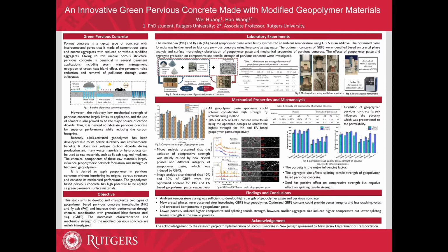After optimizing the formula, we use this formula to mix with aggregate to prepare the geopolymer pervious concrete. Here, the aggregate is limestone, and it has 4 different gradations with different sizes, denoted as F1 to F4, as shown in Table 1. After the preparation, we applied the mechanical tests, which are the compressive test and the splitting tensile test, on the geopolymer pervious concrete. These samples are cylinders with 4 by 8 inches dimension.